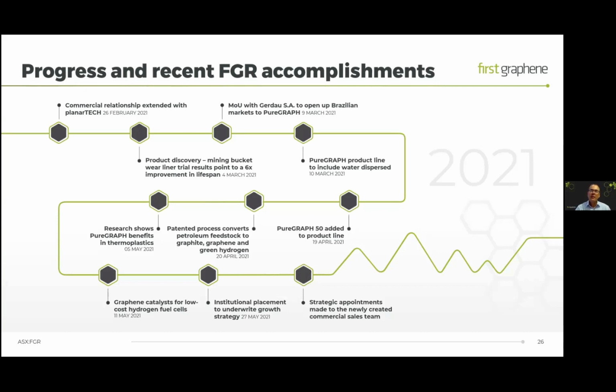So in February, we announced that we'd extended our relationship with planarTECH. planarTECH were manufacturing graphene-enhanced face masks using PureGraph, and they're now looking at a range of graphene-coated fabrics. Early in March, the report on the wear liner from the mining trial was reported, the 6 times increase, and that has since been validated by an independent auditor.